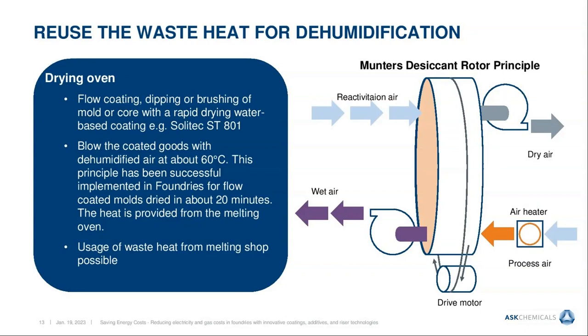We have an example of a foundry which is producing counterweights, and they coat the mold with a Solitec ST 801 at a temperature of 60 degrees with dehumidified air in only 20 minutes. And the heat, which is from the melting shop, is for free.